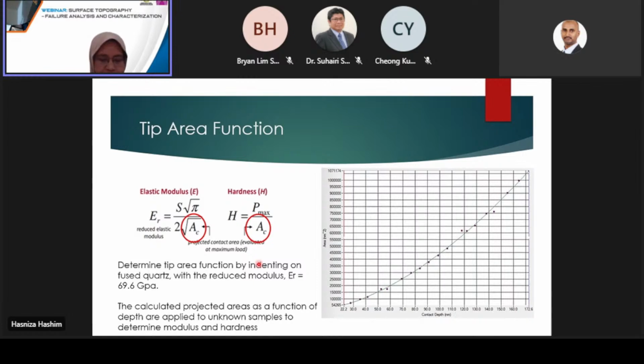As you can see from the two formulas, the projected contact area is plugged into the formula which calculates the modulus and hardness. It is very important to determine the tip area function in advance before we can do the testing. In order to determine the contact area function, we usually perform indentation using a fused quartz sample whose elastic modulus and Poisson ratio are 69.6 gigapascal and 0.17 respectively.